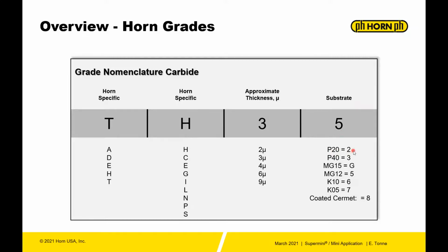So P20 is 2, P40 is 3, MG15 is G, MG12 is 5, K10 is 6, K05 is 7, and then coated Cermet is 8. So you can see, more or less, the K05, as we learned earlier, would be a 7 substrate, which I haven't seen really used on much, is extremely hard. So that would be very wear resistant, but also prone to chipping. K10 is used some within the Mini and Supermini systems, but by and large, most of the substrates are 5 substrate, which is MG12.